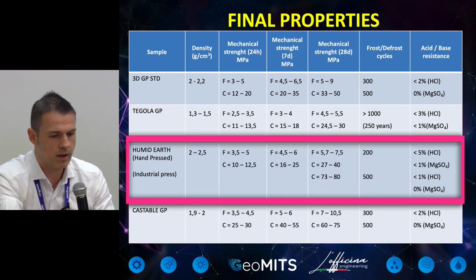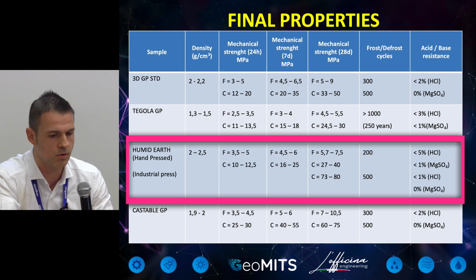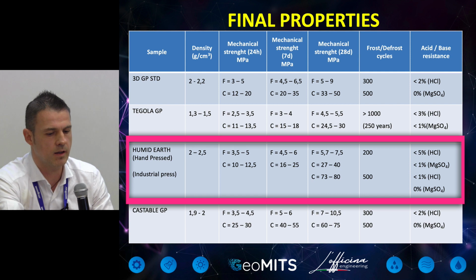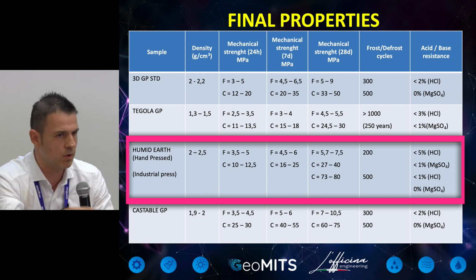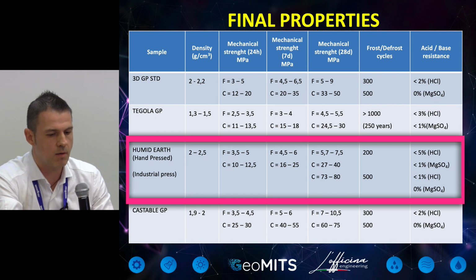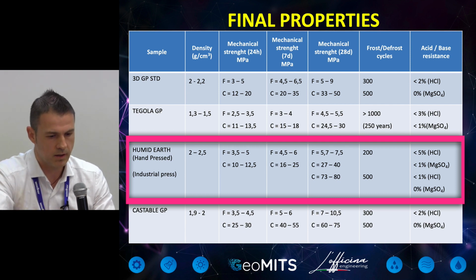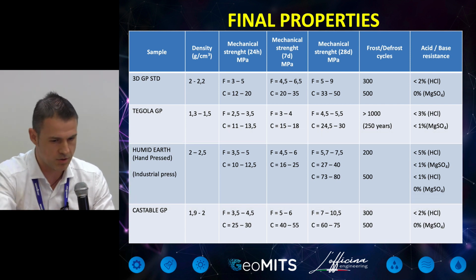And so Humid Earth, I compare my hand press product with the industrial press, because I have a client that already used this solution. So my 27 to 40 about, depending on the different quality of aggregate that I used, become 73 to 80. And this is good for the self-blocking industry to be resistant to abrasion.